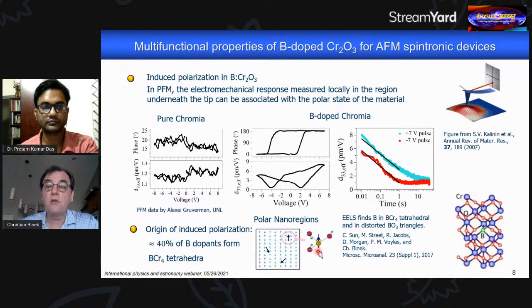Now, this is a bit more than just speculation, because again, my colleague Paul Voyles studied our boron-doped material by, as I said already, high angle annular dark field electron microscopy, but also by EELS and simultaneously by density functional theory. And he found actually that these tetrahedra here are indeed present, and it is those that are responsible for the TN enhancement. So it's the same local regions that create the TN enhancement that create these local dipoles.